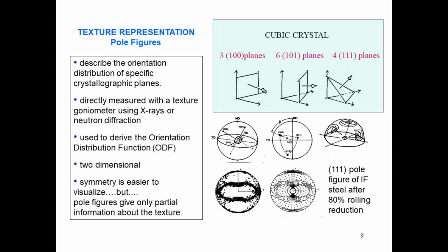So this is what it looks like if you represent points. And this is what it looks like if instead of the points you represent the density of those points. So this is the point representation of the pole figure. This is the intensity line representation. The point representation can be misleading because if you have many points in one spot, you cannot tell if the intensity is high or not because they fall one on top of each other. So you have to be careful with that, and that's why here we are going to really work with the intensity line representation of pole figures.